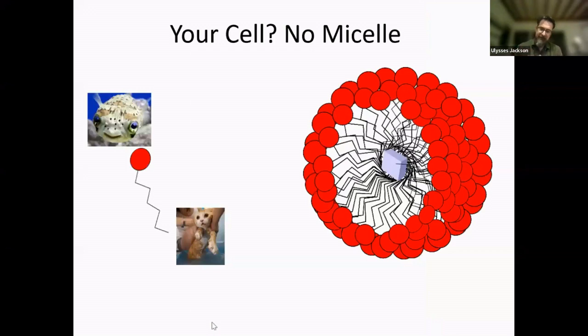It's a higher concentration in the water, and the hydrophobic portion wants to get away from the water, so it's grabbing onto that hydrophobic pigment and pulling it with it into the water until you get nice micelle structures, right? So here we have our surfactant model again, the simple model of the hydrophobic tail and the hydrophilic head. And in the center, we would have that pigment particle or polymer particle, and this micelle would be all of those structures surrounding it. And that forms a stable structure in the dispersion and keeps things floating around.